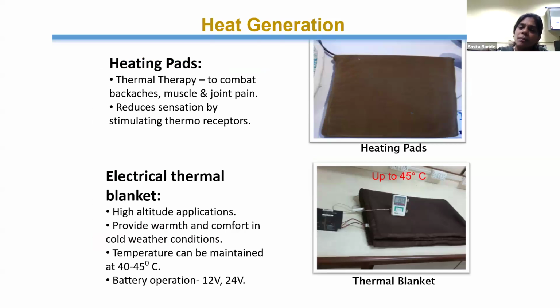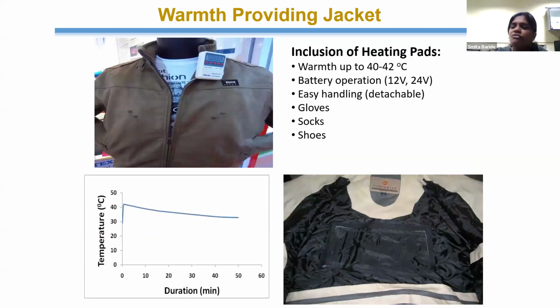Also, we have checked its performance for heat generation. Here also, we applied around 12 to 24 volts over the conducting fabric. We found that within 1 minute, about a 10 to 15 degree rise in temperature was achieved. And if we insulate it properly with an insulator, it remains hot for around 50 minutes.